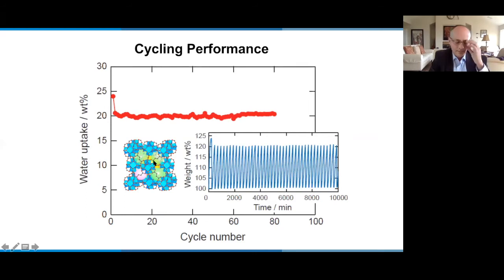This is MOF 801 made from the zirconium clusters and fumaric acid. We did the uptake and release of water from it, in this case over many cycles, like 80 cycles, without loss of capacity. So the MOF is very stable in water. You can do many cycles without any hysteresis. We saw after the first cycle, there's a slight drop in performance.